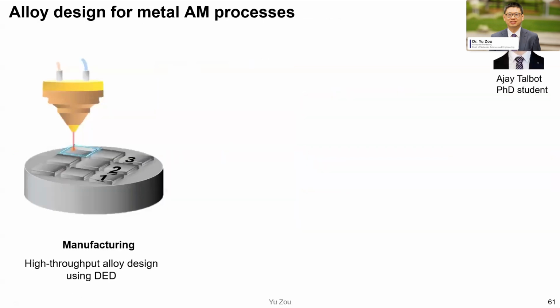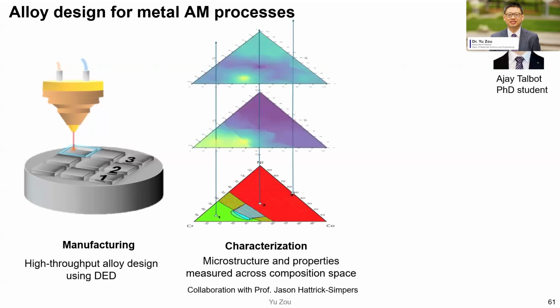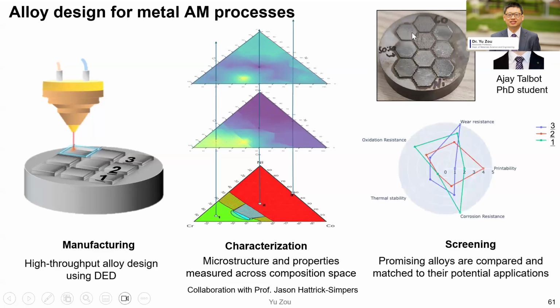Towards the material science, we also use additive manufacturing method to identify special alloys for additive manufacturing. For example, we have a project about the high throughput alloy design using DED. During the printing process, we can control the feeding rate between 2 or 3 powder feeders and control their compositions. And then we can test the samples in different compositions and identify their performance, like wear, oxidation, corrosion resistance, and also printability.